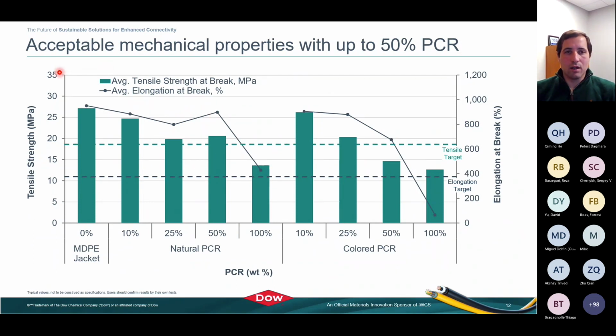The mechanical properties are really where you start to see some of the different deviations when you talk about the PCR materials and the randomness of the type of material that you get. So you can see the control to the left-hand side with very good tensile and elongation properties. But as you go higher and higher in PCR content, the biggest drop is really in the 50 to 100% on the natural PCR, but definitely at the 100%.